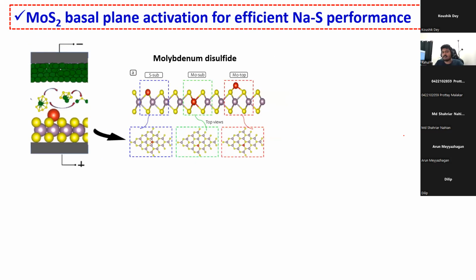Okay. Now this is another work where we worked on MoS2 based material. Basically, we all know that MoS2 is a semiconductor, a direct band gap semiconductor with a band gap of 1.6 electron volt, right? In previous literature, you can find that MoS2 edge sites are active for polysulfide adsorption. So if we have to increase the catalytic efficiency of a substrate or a material, basically we have to increase the active sites, right? We all know that the edge site is active, but if we can make the basal plane active for the polysulfide adsorption, then both the basal plane as well as the edge site will be active, and the more efficient the catalyst will be.